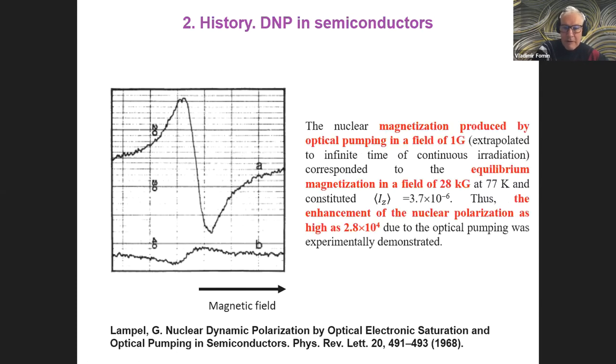3 orders of magnitude. This comparison is given in the next slide, but the value which was measured is really small, as is typical for nuclei, but it's confidently measurable. And the enhancement of the nuclear polarization in this case was as high as 2.8 times 10 to the power 4. So I think this experimental work has remained a motivator for all subsequent